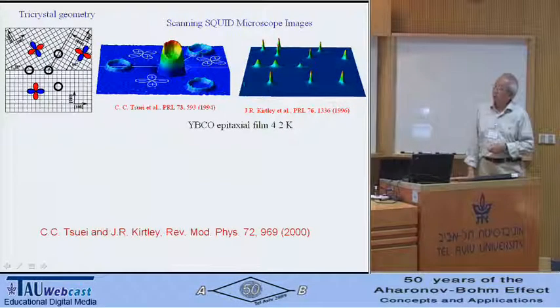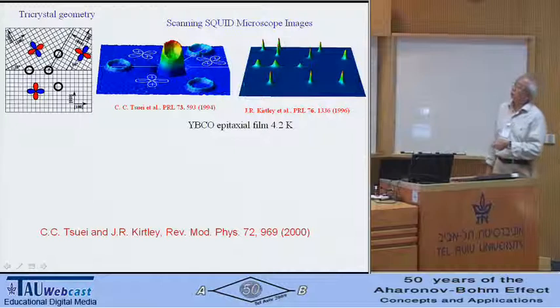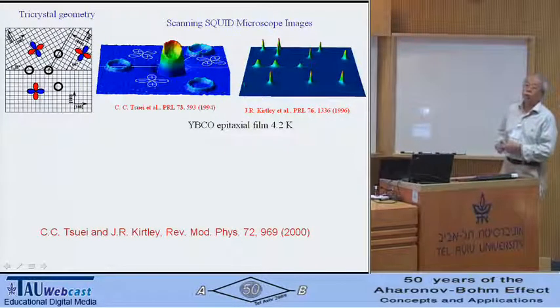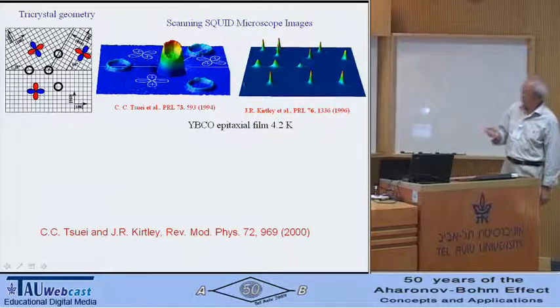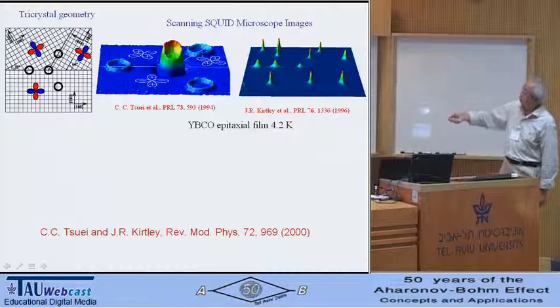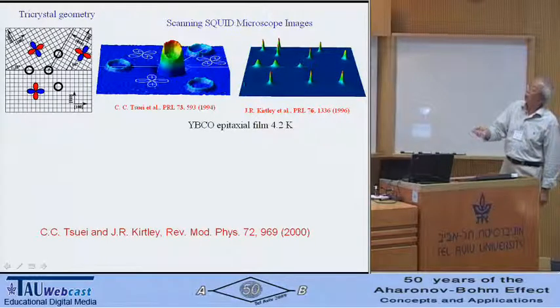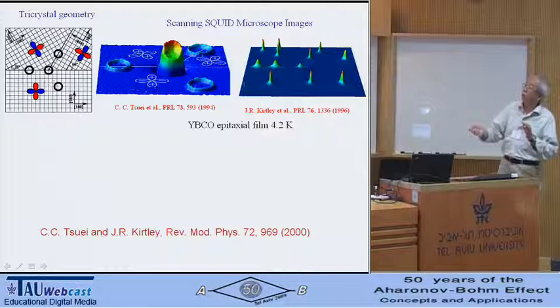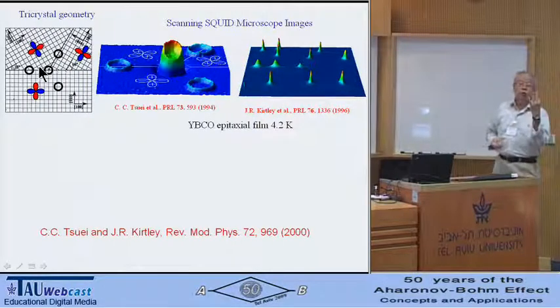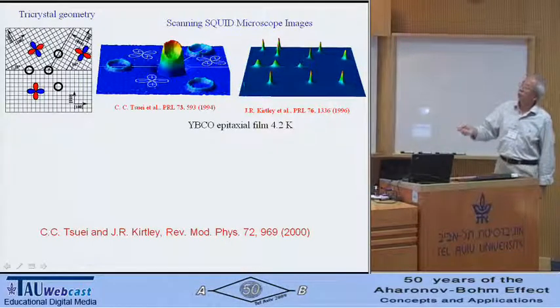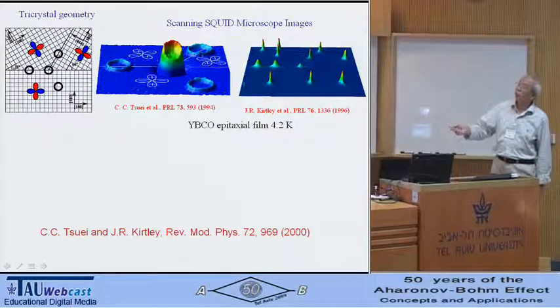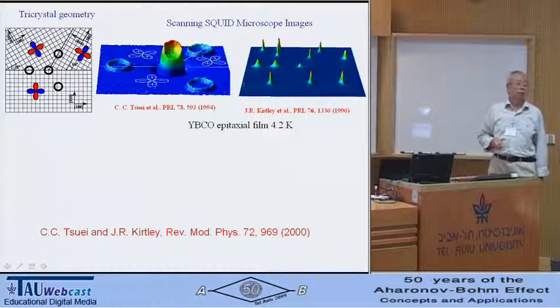I designed an experiment with a substrate consisting of three crystals specifically oriented such that, if it's a D wave, and if you pattern a high TC film ring on it, then at the tricrystal point it has three junctions and changes sign once. Therefore, if it's a D wave, like I showed here, it should show a half flux quantum at the center ring, but not the other ring. The other ring is just the control of my experiment.